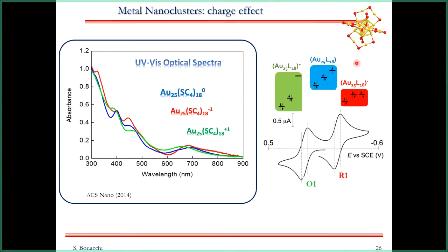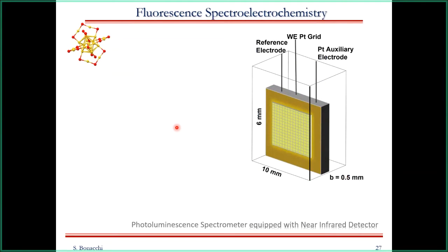I would also like to point out here that the gold 25 neutral form is a radical form that is very peculiar, and it also has an interesting aspect when you talk about magnetic properties of a cluster. However, we first performed the spectroelectrochemical analysis of the optical properties of this cluster, and then we used the same approach to perform fluorescence spectroelectrochemistry. What we found out: we used this setup inside a spectrofluorimeter equipped with a near-infrared detector, sensitive up to 1070